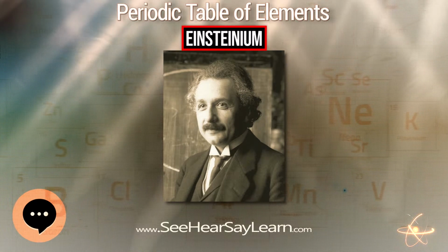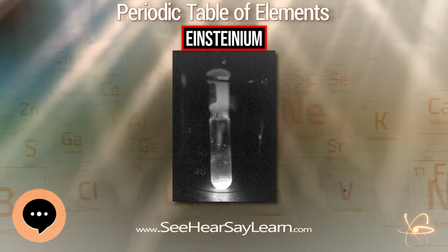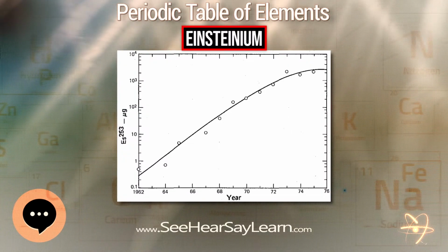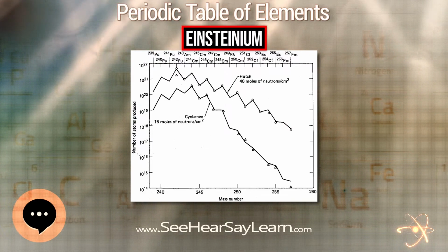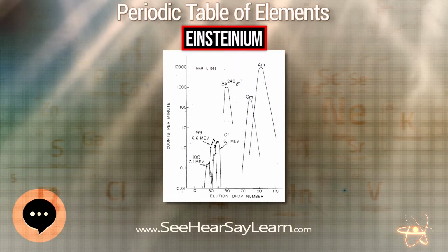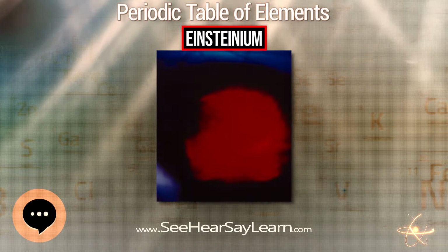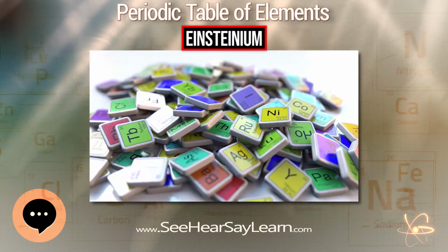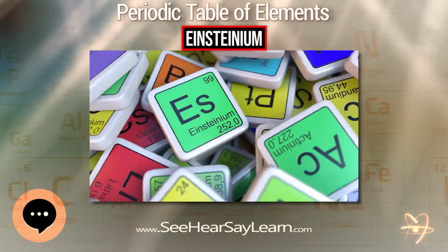Einsteinium oxide was obtained by burning Einsteinium nitrate. It forms colorless cubic crystals, which were first characterized from microgram samples sized about 30 nanometers. 2 other phases, monoclinic and hexagonal, are known for this oxide. The formation of a certain Es2O3 phase depends on the preparation technique and sample history, and there is no clear phase diagram. Interconversions between the three phases can occur spontaneously, as a result of self-irradiation or self-heating.